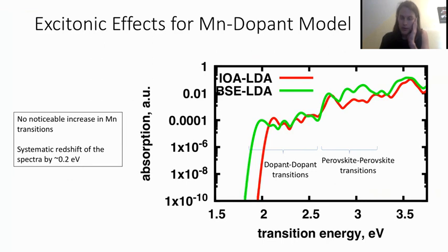So previously in a couple of group meetings, I presented on exploring the modules in VASP which allowed us to compute Bethe-Salpeter exciton spectra. I didn't put in any of the details here, but essentially I took one of the models that Salim had for his dopant and computed spectra in our usual method, which is the IOA, or independent orbital approximation, and then compared it to what VASP provided from doing a Bethe-Salpeter equation, which is an extension of independent orbital that includes Coulomb and exchange interactions. And those are compared in this figure.